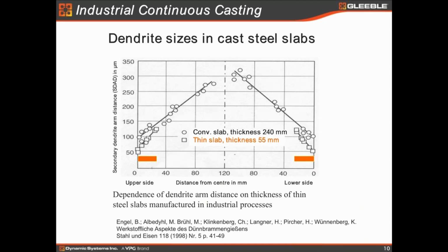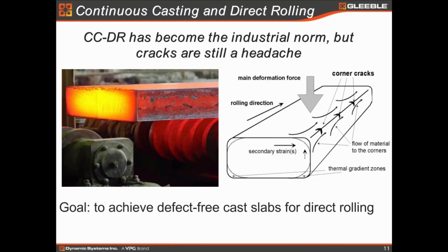And this one shows the secondary arm spacing distance as a function of the thickness. That's not really something new, but we all know it. So we talk about casting, and continuous casting and direct rolling. The key here is, if we want to do continuous casting and direct rolling, we have to make defect-free billets. If you have lots of defects on the surface, whether in the corner or the edge, or longitudinal or transverse, you cannot do direct rolling, because you cannot roll the defects into the steel strips, right? In the conventional way, you have a surface treatment, but that's not the way to do continuous casting and direct rolling. So producing defect-free castings is the key to CCDR. But the question is how we can achieve defect-free cast slabs or thin strips for direct rolling after that.